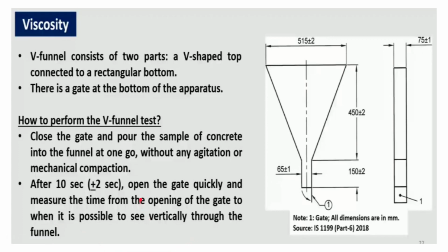Initially we pour the concrete, and then after 10 seconds we quickly open the gate. Then we measure the time from the opening of the gate to the time when we can see completely, vertically through the funnel. From the top we can see what is there in the bottom. So the time taken after opening the gate we have to measure.